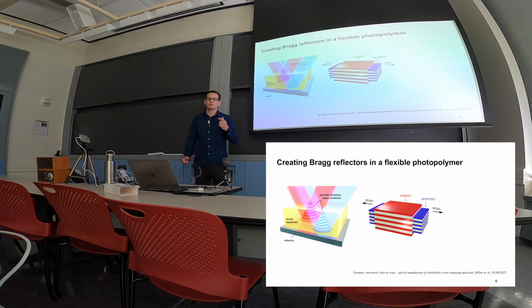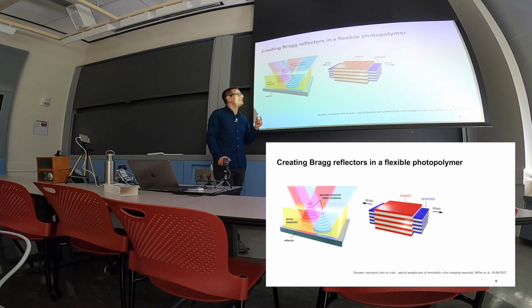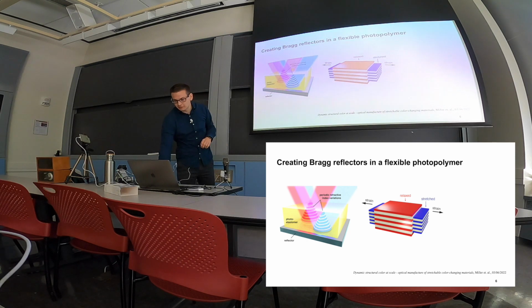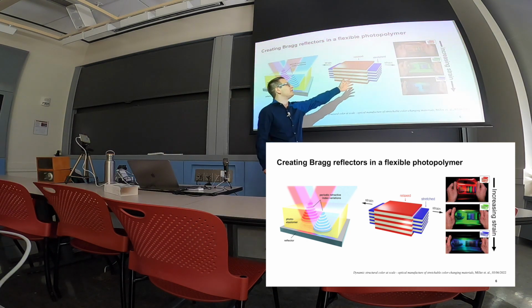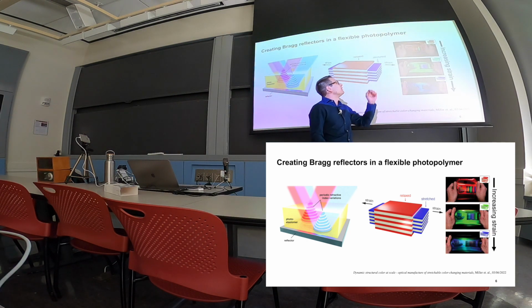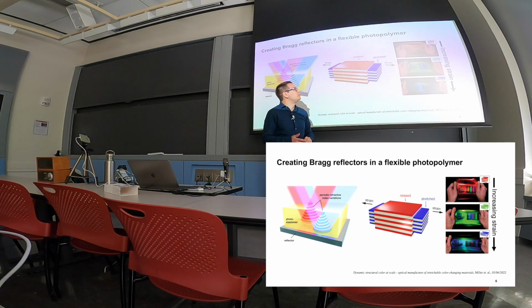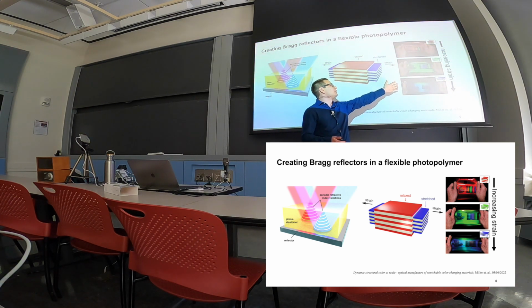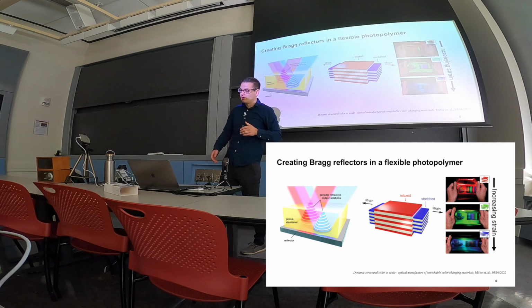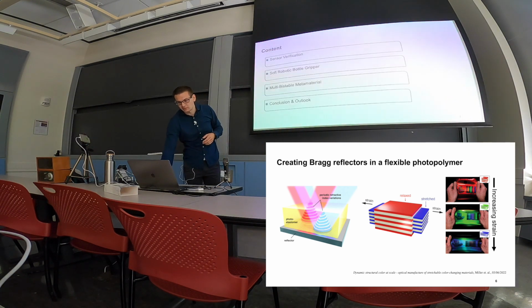And as we imagined from the slide before, once we have a thinner layer thickness, other wavelengths will be reflected as a peak wavelength, and therefore we can create different colors, as we can see here on the right slide. Like when we have the Bragg mirror created with the red wavelength being at the peak wavelength that is reflected, then once we increase the stretching, we shift through the whole spectrum, so green and blue.